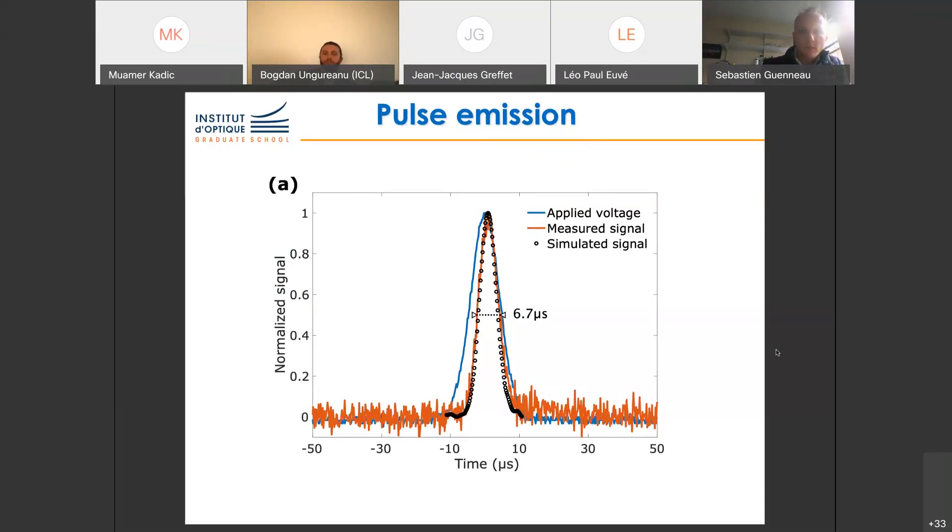After a long fabrication development, we end up with a device 100 microns by 100 microns. To demonstrate short light pulses, we send a 10-microsecond Gaussian electrical current pulse through the system. The simulated signal — shown with dots — comes from measuring the device temperature via its electrical resistance: platinum has a resistivity that depends linearly on temperature, so the device acts as its own thermometer. Plugging this measured temperature increase into Planck's law perfectly reproduces the dynamics of the emitted optical signal.